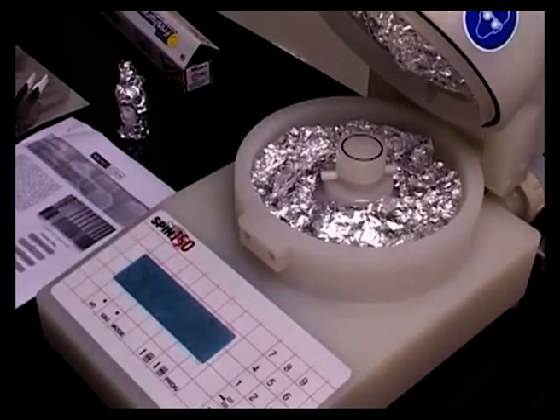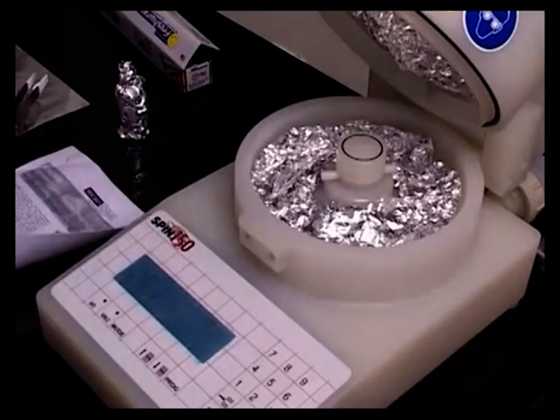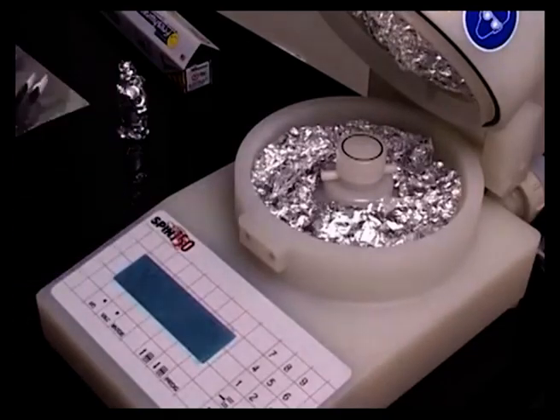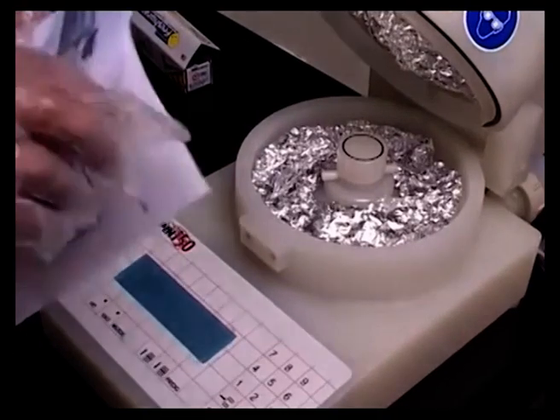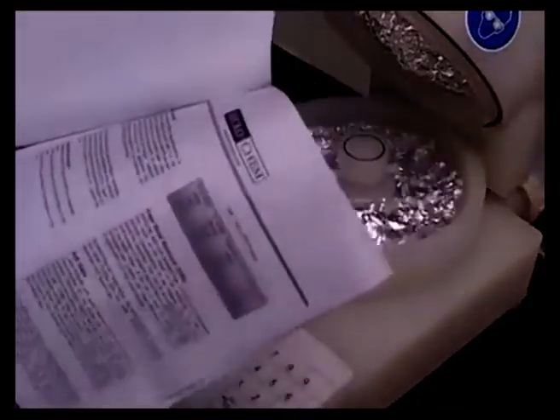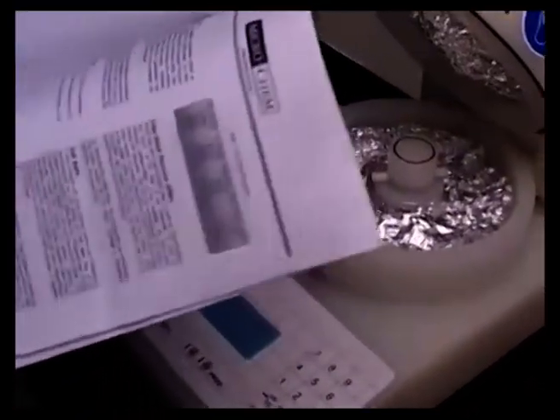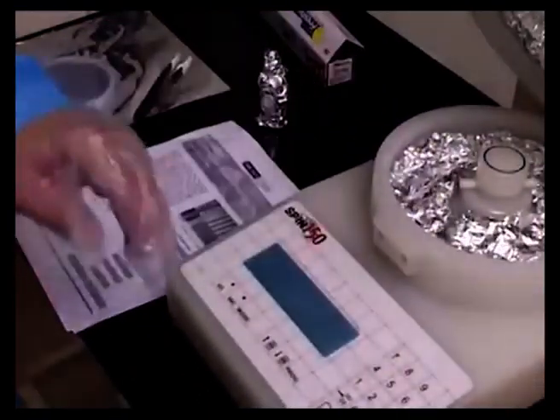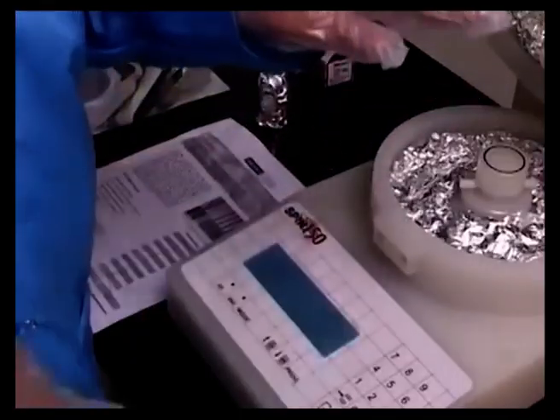So in this particular example, as per the resist manufacturer specifications, the spin speed that we are using is about 3500 RPM, and the spin speed has to be attained with an acceleration of about 300 RPM per second. It also mentions that you have to hold at a certain spin speed for close to 90 seconds for the spin coating to be uniform. I would also like to illustrate here that the resist, being a thick material, needs a little bit of time for uniform coverage over the whole surface.